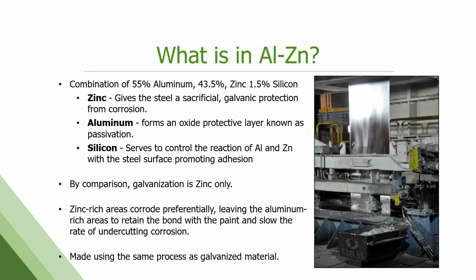So what happens is these zinc areas in that structure are going to corrode preferentially, leaving the aluminum rich areas in that structure. And as you saw in that last picture, there's a lot of that aluminum left. So now you still have a good bond of the aluminum to the steel, and then the aluminum to whatever coating or paint you've put over the top, even though the zinc areas are gone over time.